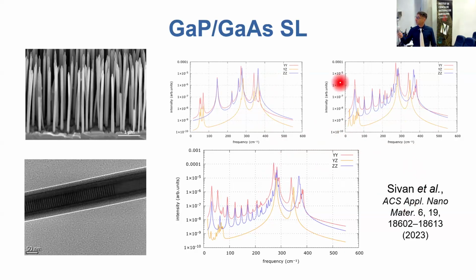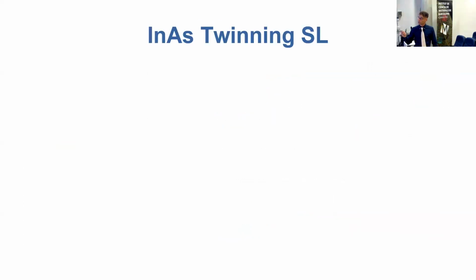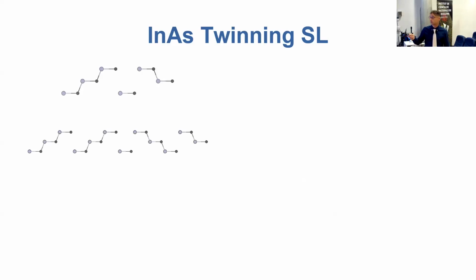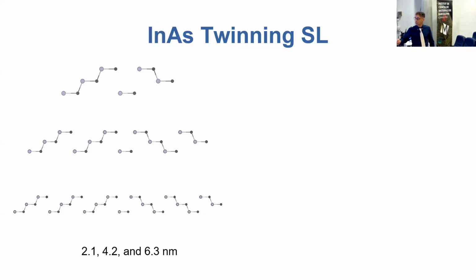And apart from these superlattices, we also studied a special kind of superlattices which go under the name of twinning superlattices, where the superlattice structure is not provided by chemical switching between atoms of different species, but from the mirror imaging of the primitive cell of the superlattice with itself. So you can really appreciate this sort of transition between 2 different geometrical or chiral configurations of the very same material. And in this case, interestingly enough, we could simulate up to 6.3 nanometers.